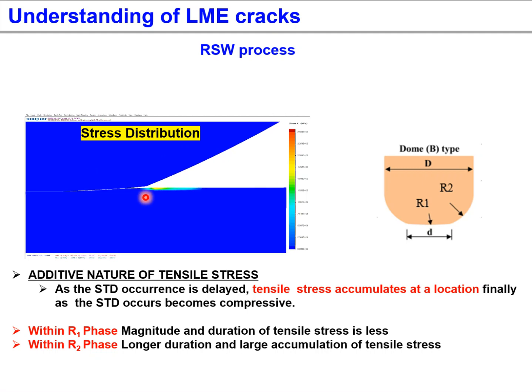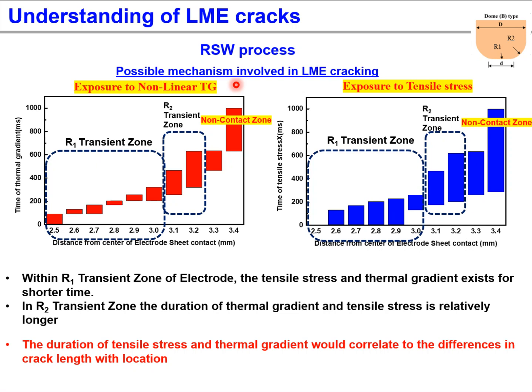However, when R2 phase contact has been made, the duration of the tensile stresses becomes very long, and large accumulation of tensile stresses could be possible. Based on the simulation data, we have measured the duration time of thermal gradient and tensile stresses at R1 radius zone and R2 radius zone respectively.